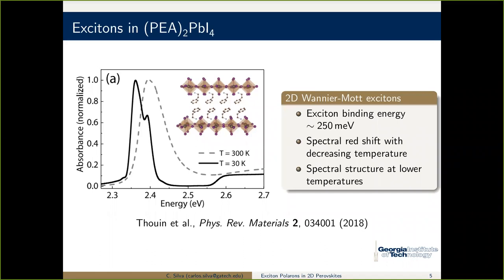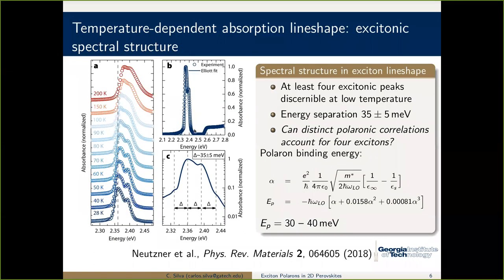And you'll see that through the coherent multidimensional spectroscopy. Those couplings to the lattice are distinct for the different excitons, and they are governed by the exact electron-phonon coupling to specific modes, which are different for the different excitons. Their binding energies turn out to be different for that reason. So that's what I'm going to tell you. I'm going to show you that next, throughout the rest of the presentation.